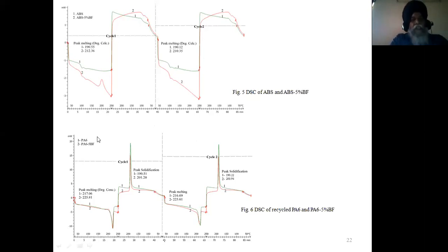So you can see on this, along the x-axis, what I have done is I have raised the temperature from room temperature to 250, and then from 250 to room temperature, then again from room temperature to 250, then again 250 to room temperature. And you can see on the same axis you have time also. So the whole cycle was allowed to run for 85 minutes. Like most of the thermoplastics that we work with, they work in the range of up to 300 degrees Celsius temperature. So depending upon the application, you can select a particular range of the thermoplastic material, and you can see how this material behaves in a particular heating and cooling cycle.